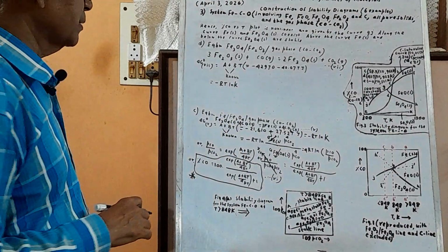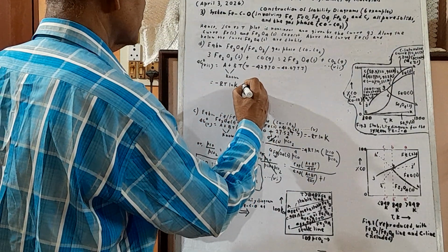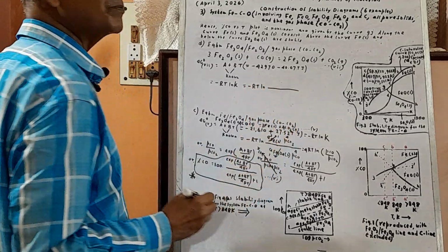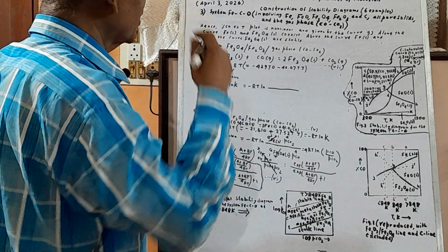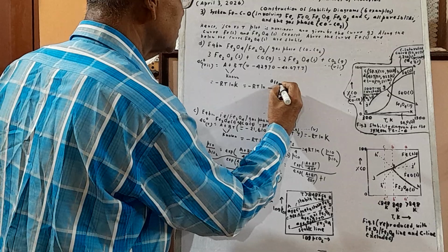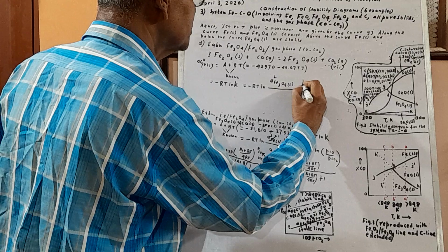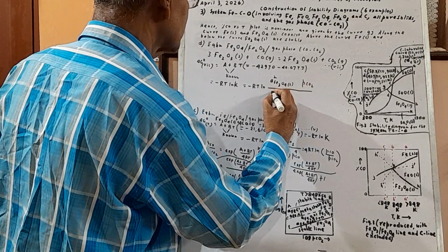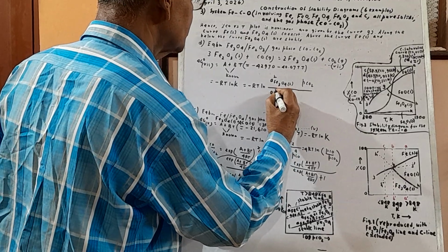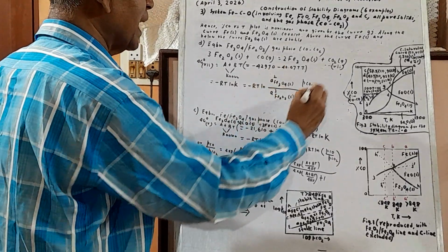Minus RT ln K, you know what this is? Then you keep on writing like this. Minus RT ln K is minus RT. What is your K? K is the activity of Fe3O4 solid squared, PCO2 over the activity of Fe2O3 solid cubed, PCO. Again I repeat, if you are interested, right here at equilibrium.